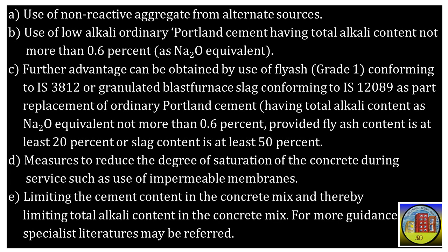D. Measures to reduce the degree of saturation of the concrete during service such as use of impermeable membranes. E. Limiting the cement content in the concrete mix and thereby limiting total alkali content in the concrete mix. For more guidance, specialist literatures may be referred.